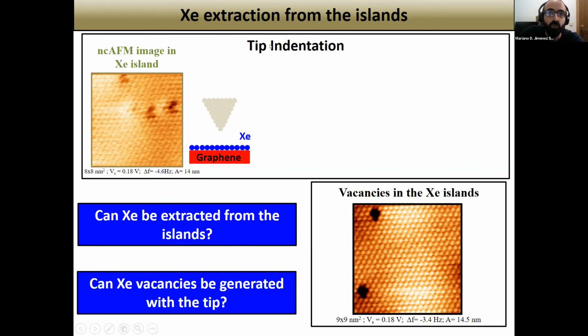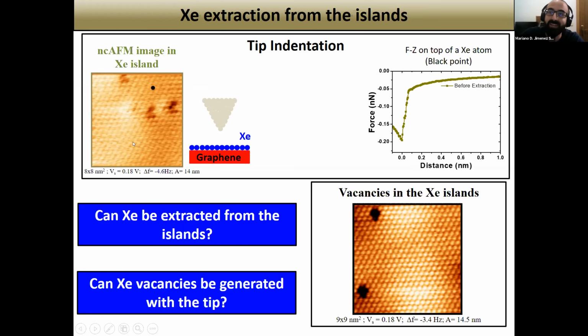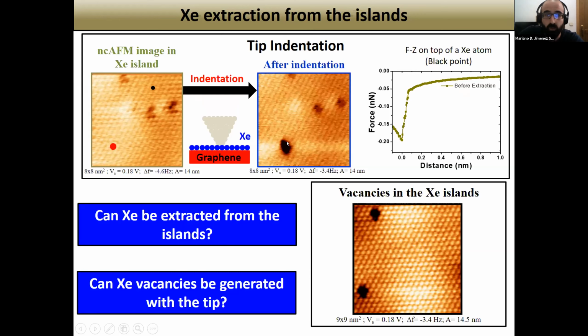The first one was to indent the tip. Here I show you the region where we have performed the indentation. Before doing so, the stripes are related with the atomic periodicity of the xenon. Before performing the indentation, we have characterized the tip by means of a force distance curve, which has been acquired at this point. Well, after this characterization, we have indented the tip. And how does the region look after the indentation? Well, we observe that we have generated a big vacancy on the xenon layer.